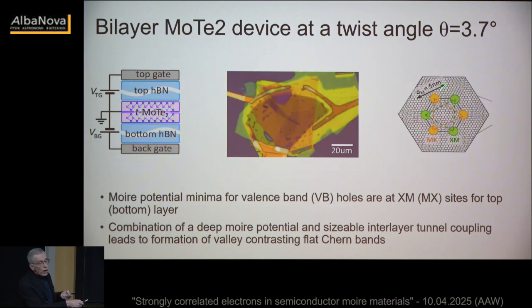Now, here you have the maxima of valence band, minimum for holes, and there's also maxima for the conduction band. So that's actually a maximum for the electrons. So it's almost like what you would have in an electrostatic scenario. If you have an electrostatic potential that is varying spatially, then electrons and holes would see exactly the opposite potential, because one will be attracted, the other one will be repelled. And then if you move around, you'll have gradients, so there will be a second order moire effect that goes as these electric field squared, but the average potential seen by the exciton will be identical.